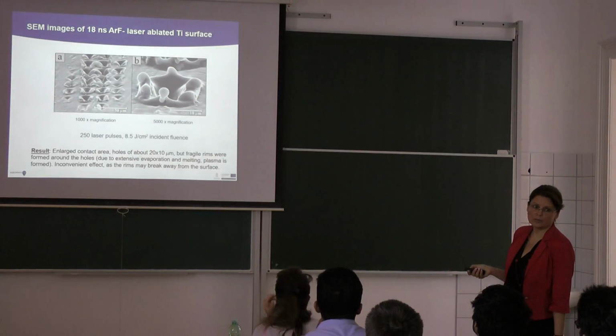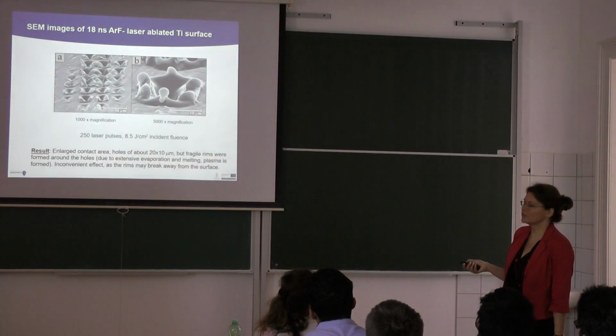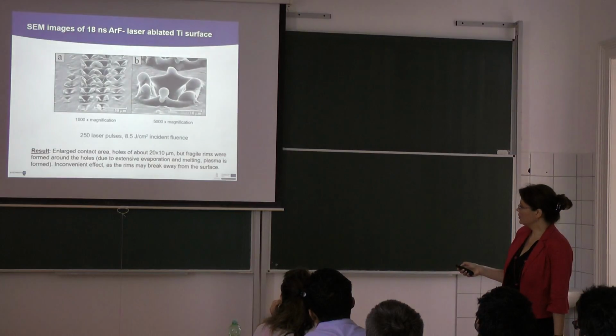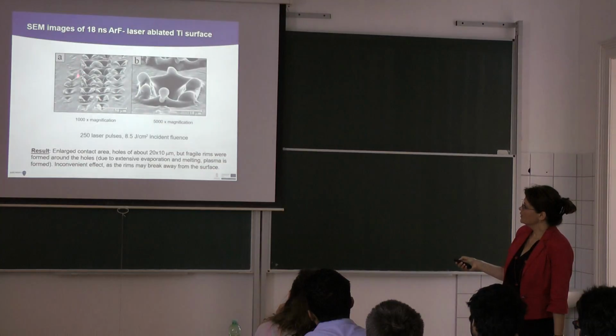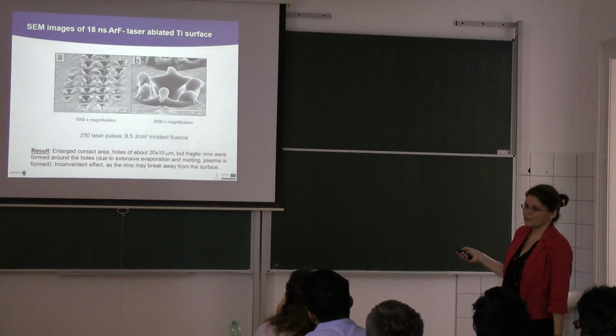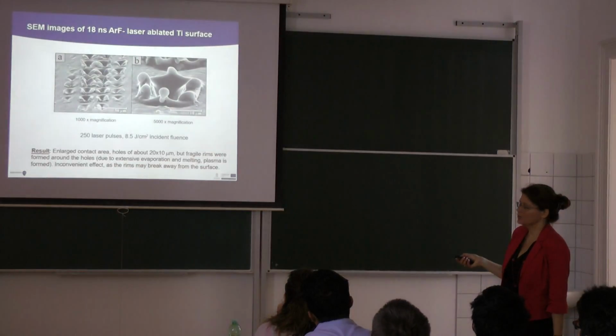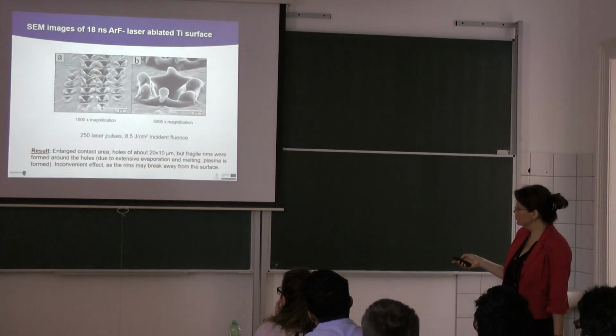Then we applied the 18 nanosecond argon fluoride excimer laser, which is available at the experimental physics department for optics. And you can see here the shadow of the copper grid. So the laser beam was attacking this surface, but unfortunately you can see also some melted particles which can come out and have a toxic effect in the human body. So it is not a very good laser ablated surface.